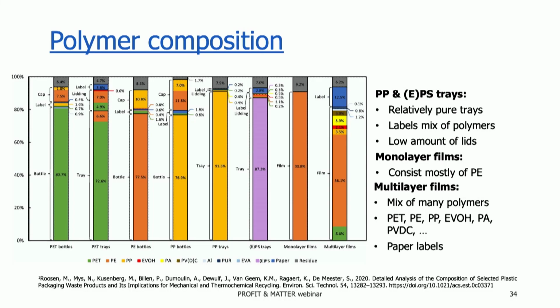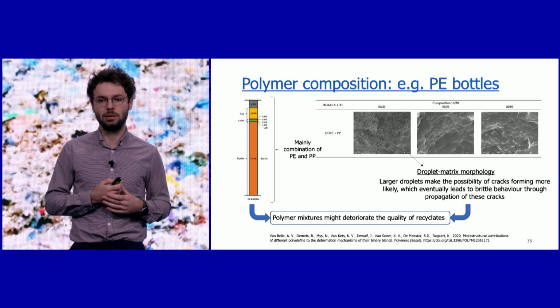For the film stream, we made a distinction between monolayer and multilayer films. The monolayer films mostly consisted of polyethylene, but for the multilayer films, we saw that many different polymers were present, among others PET, PE, PP, EVOH, polyamide, and so on. Also, sometimes those multilayer films contain a certain paper label.